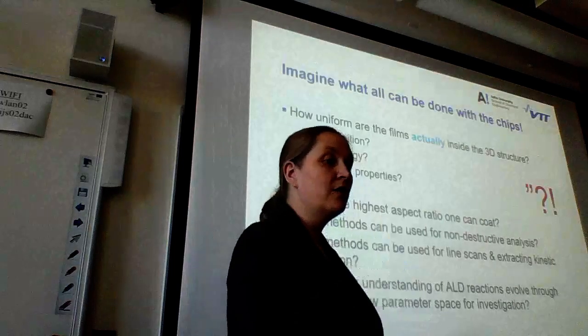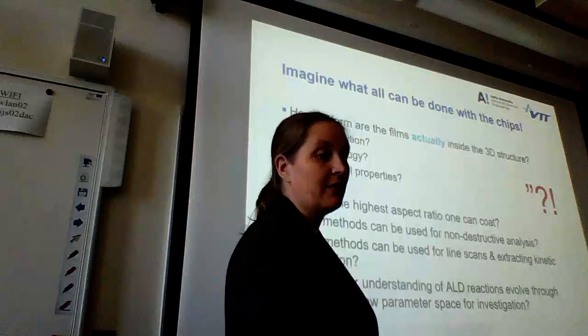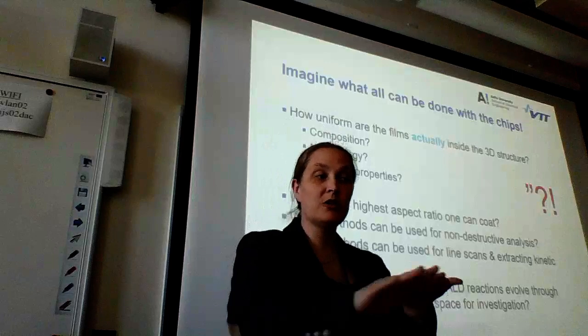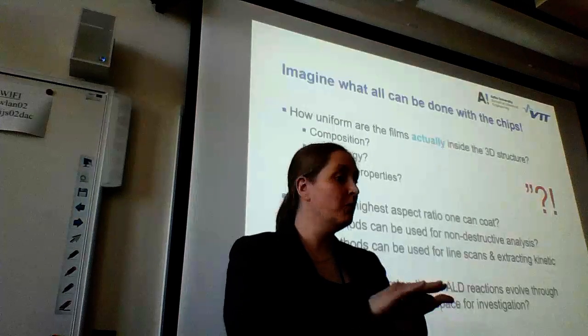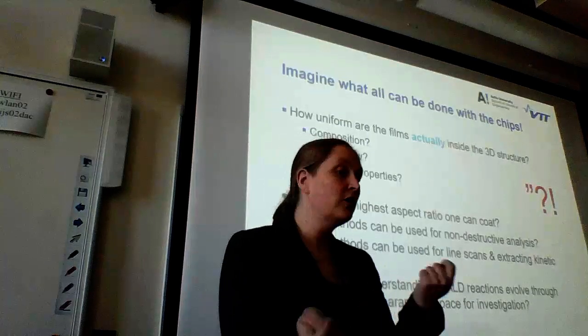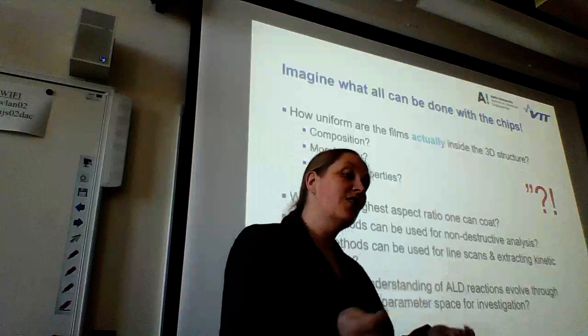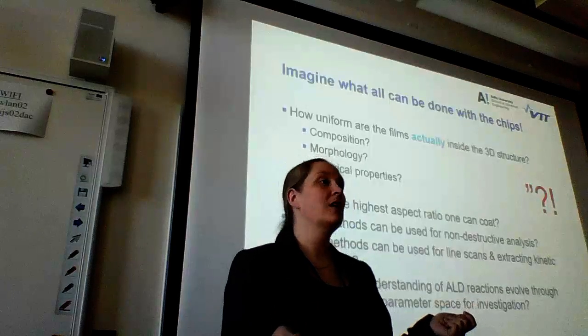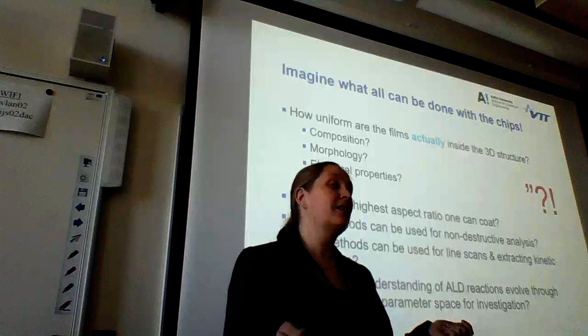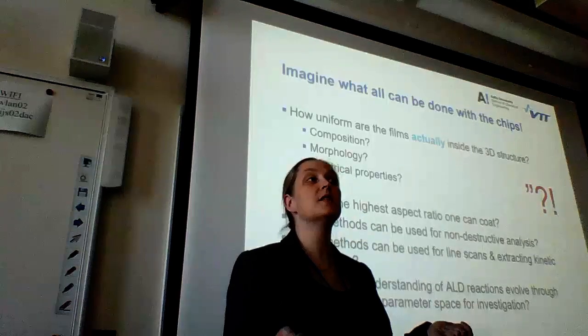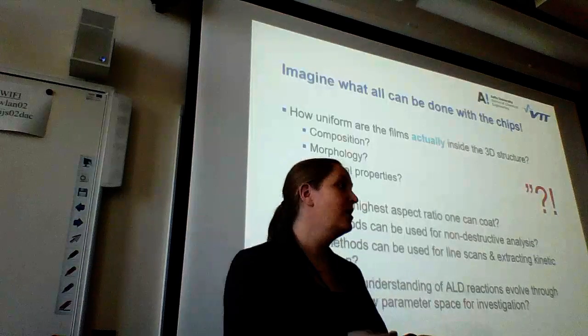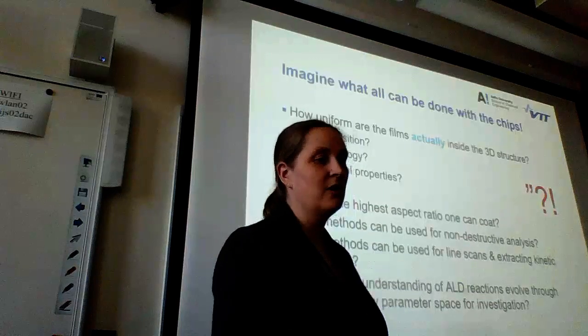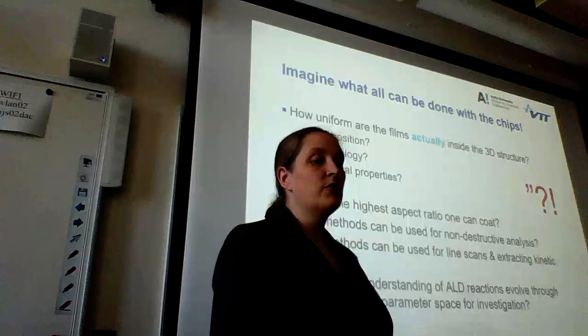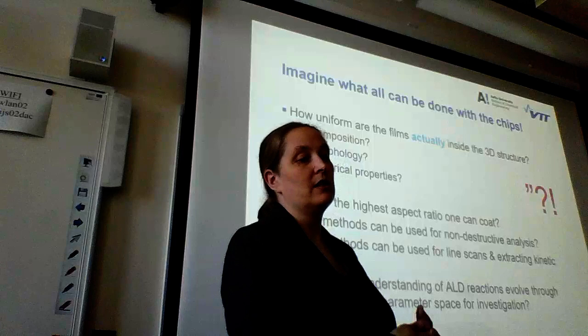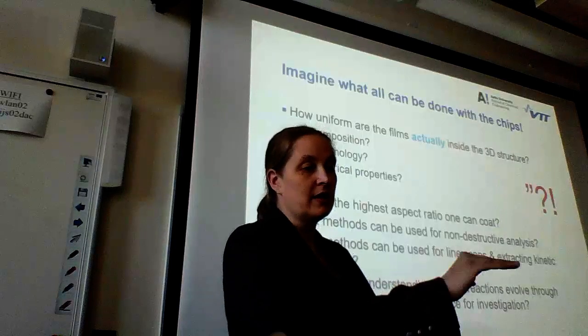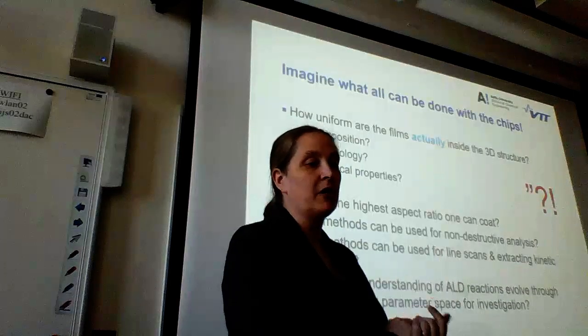How uniform are the films actually inside the 3D structure? Does the composition stay the same? Does the morphology stay the same? How about the electrical properties? What's the highest aspect ratio one can coat? At the moment, the record is at 3,000 to 1 with these pillar hole test structures. Who can go and which process can go deeper? What methods can be used for non-destructive analysis? What methods can be used for these line scans and extracting kinetic information?